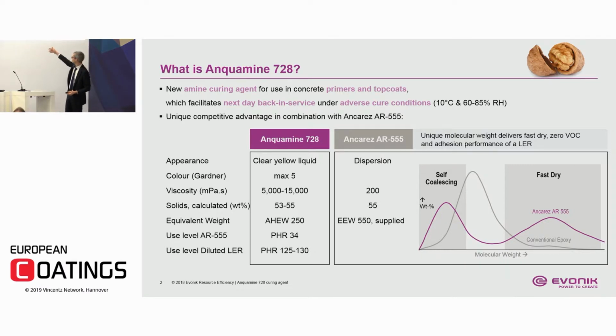It has a different molecular weight dispersion. We start from a different base. We start from a liquid epoxy resin base. And as a result, you see some of that liquid epoxy resin on the left-hand side, the lower molecular weight, still in there. And that helps for the coalescing. At the same time, you have a higher molecular weight component that gives you the Fast Dry, that gives you the fast cure speed. So the combination of the two is ideal to actually help films cure at low temperature, form good film, and get a good adhesion on the total system.